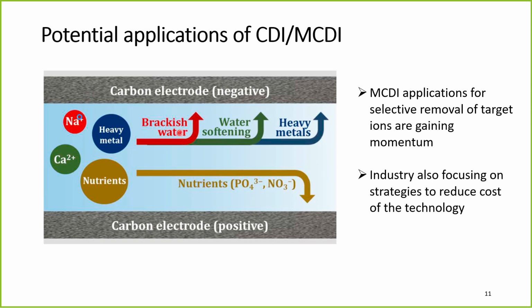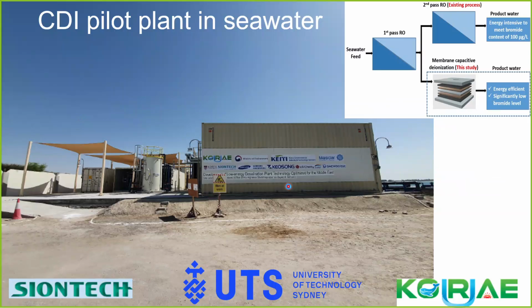People try to apply it to brackish water, to make drinking water quality less than 500 milligrams per liter. Also water softening to remove some of the calcium and magnesium, and also remove arsenic. Some contaminants, arsenic or specifically nitrate in groundwater, are less tedious, but the problem is that toxic heavy metals and nitrate compounds can only be removed specifically using this MCDI technology. So this is the more cost-effective process.